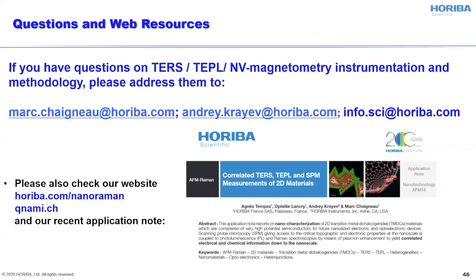Great, thank you. I have two questions here that seem to be connected. What's the spatial resolution of TEPL on TMDs? Can you do both linearly polarized and circularly polarized TEPL with similar spatial resolution? So in terms of polarization, in tip-enhanced experiments, the polarization will be governed by the dipole moment of the tip itself. So realistically, I'm not sure whether the original polarization will stay in the enhanced signal.